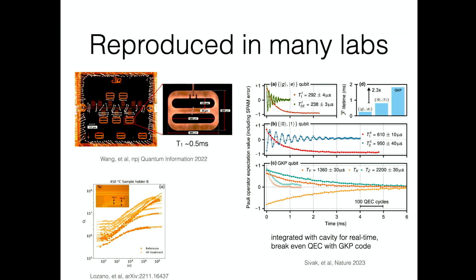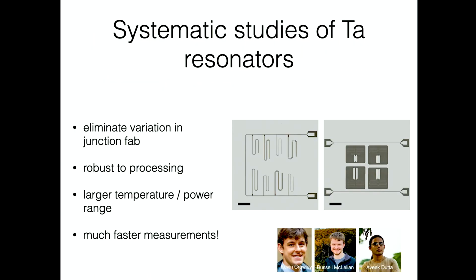And since our work, this has been reproduced in many labs. So there was a group in China that was able to get to T1s of 0.5 millisecond. There's a group in Belgium at IMEC that has also developed tantalum on silicon, where they're able to get to these Qs of a few million. And Michel Devoret's group at Yale took a tantalum qubit and integrated it into the GKP code to realize the first sort of break-even quantum error correction. So tantalum was one of 3 or 4 improvements to make that happen.